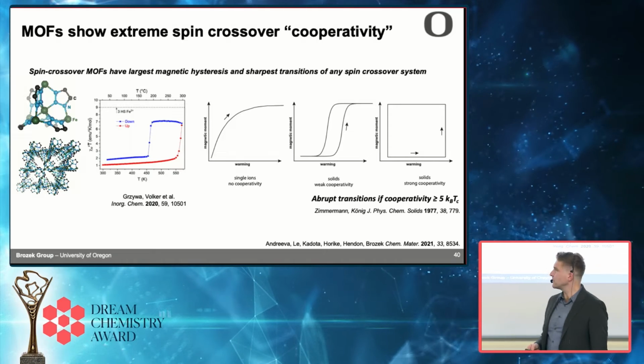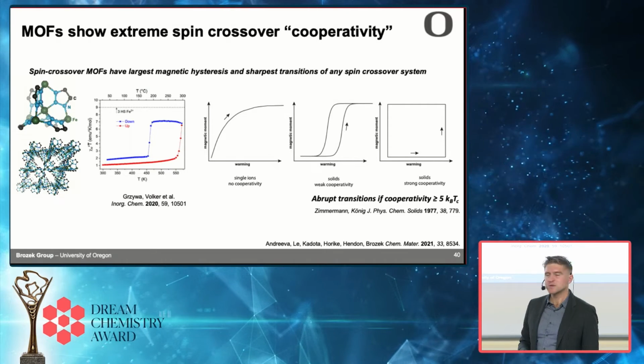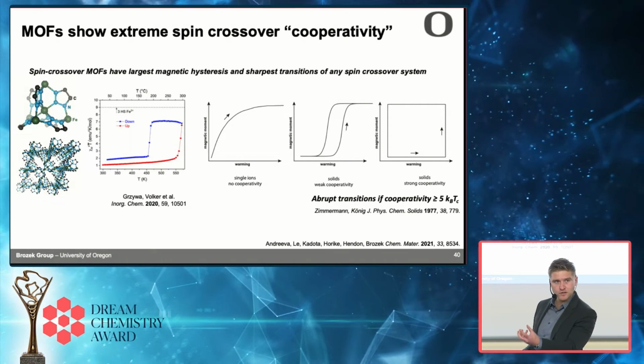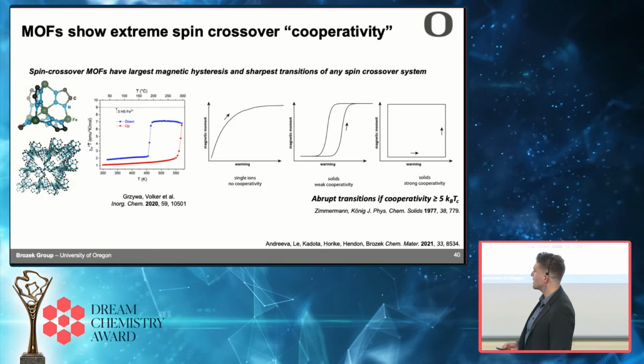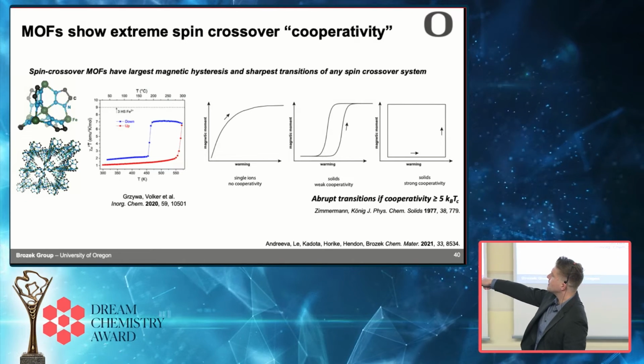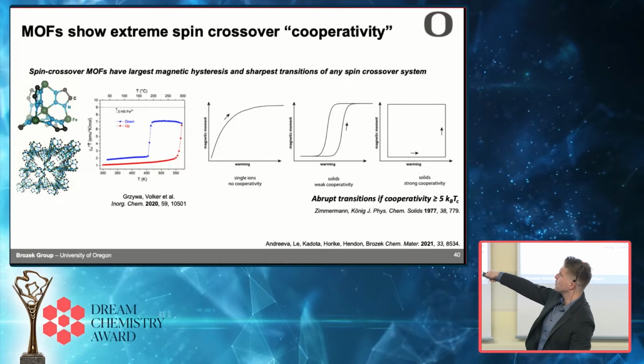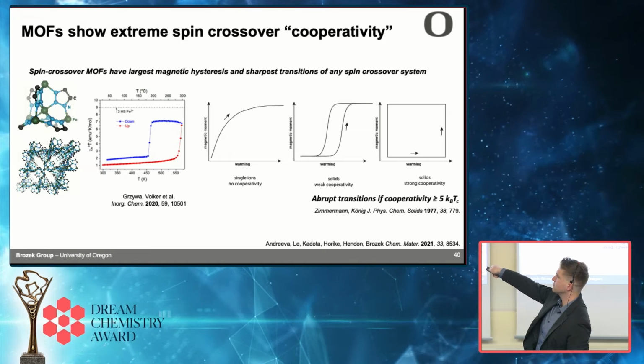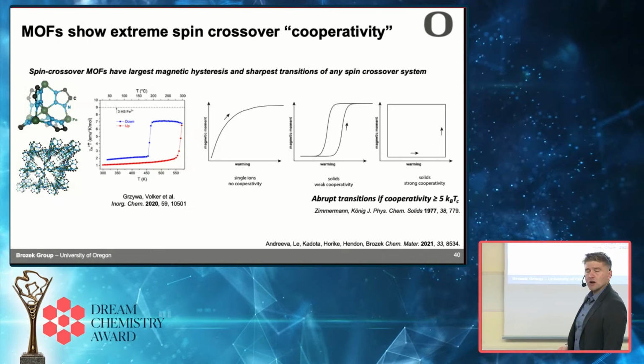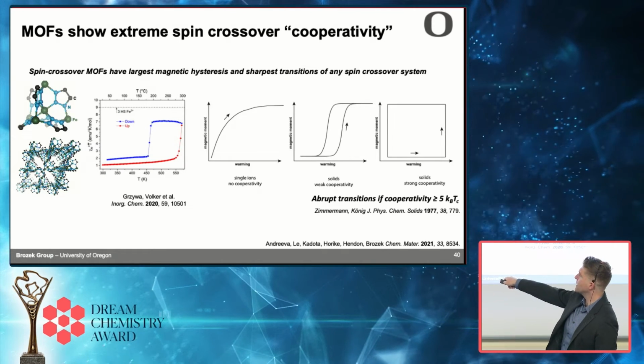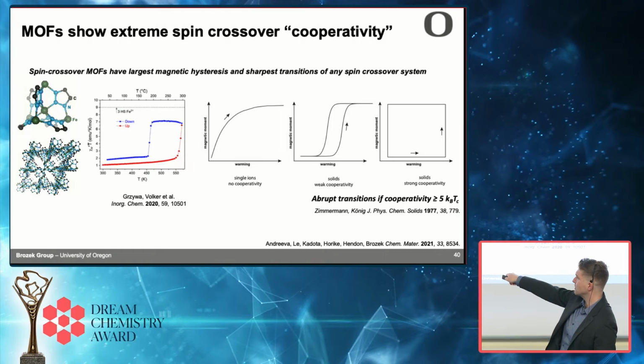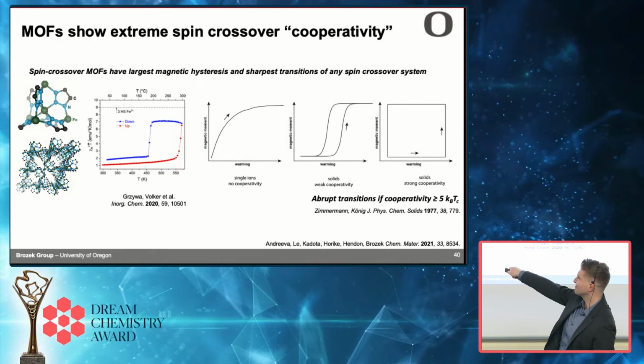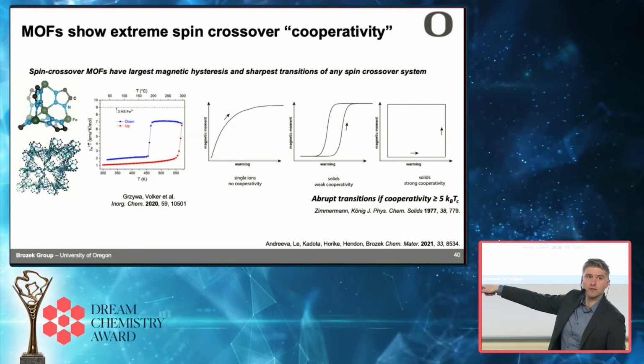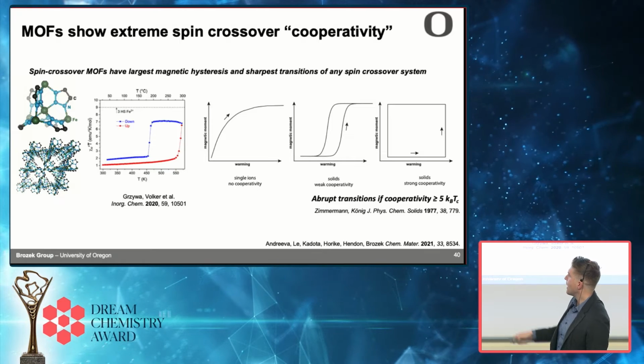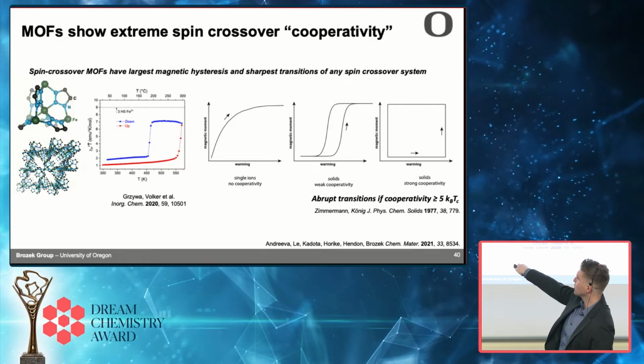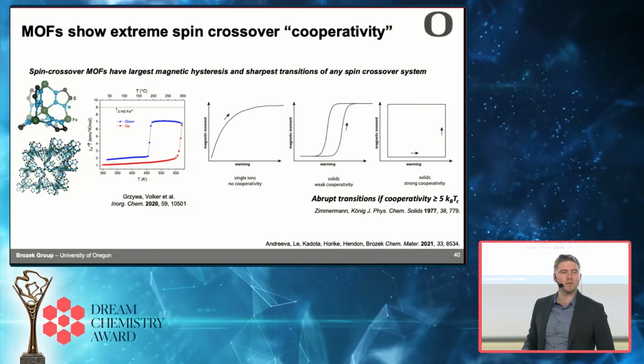for other molecules or materials that undergo spin crossover, so if you have a molecular crystal and you measure its magnetic response, as you heat it up, you just get this very gradual population of the high spin state. Most spin crossover materials look something more like this. There's a hysteresis window, but it's more gradual.